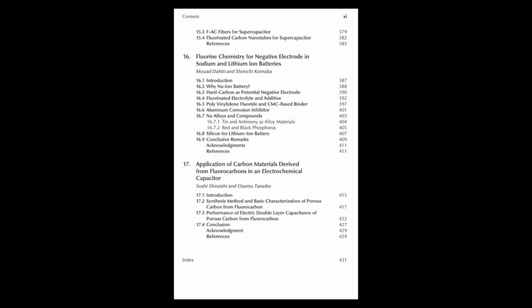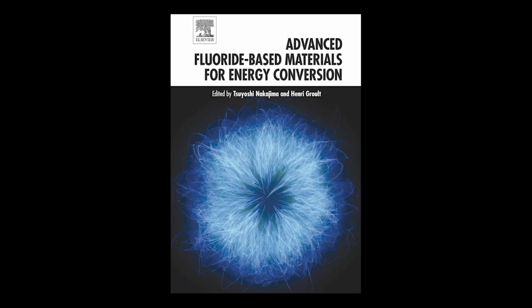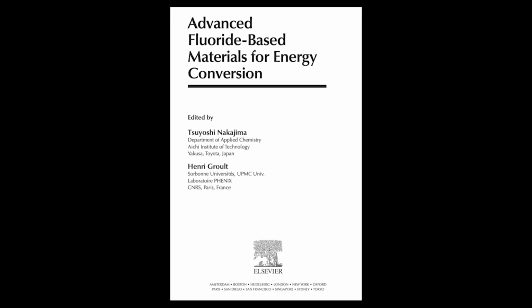And the source even provided visual evidence, right? Electron microscope images of the cathodes after they've been used. Yes, they did. Figure 1.27 provides really compelling visual evidence. After being cycled at 55 degrees C, the LNMO cathode using the conventional Gen 2 electrolyte shows this significant coating. Looks like gunk, really. Okay, indicating breakdown. Yeah, indicating the electrolyte is breaking down.